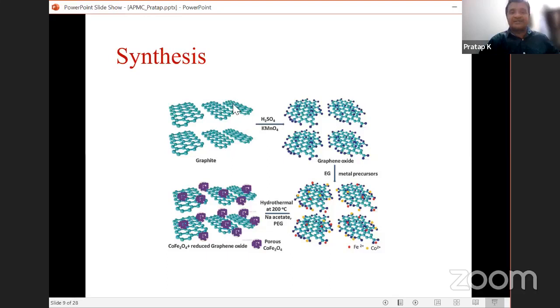This is the graphite, and we are preparing graphene oxide by the modified Hummers method. Using the solvothermal procedure, we add the metal precursors, ethylene glycol and so on, and we prepare cobalt ferrite anchored on the graphene sheet. So this is the reduced graphene sheet with cobalt ferrite on it. This is the schematic of the synthesis. Graphite to graphene oxide is obtained by the modified Hummers method, and from that, the composite of reduced graphene oxide and cobalt ferrite is obtained by the solvothermal method.